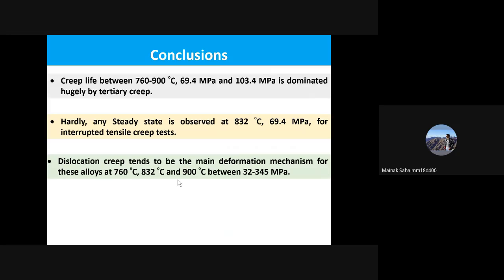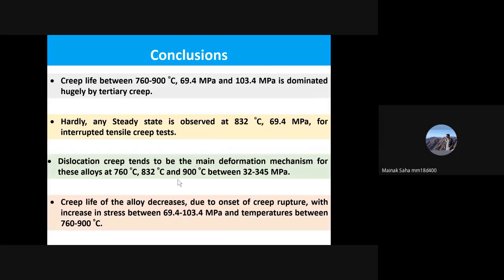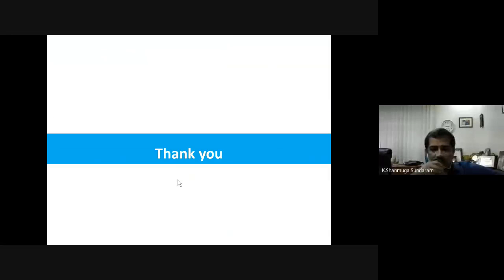Then fourthly, and most importantly, the creep life of the alloy decreases due to the onset of the creep rupture, which I have discussed in the earlier slide, with the increase in the stress between 69.4 to 103.4 MPa and at temperatures between 760 to 900 degrees. So with this, I would like to conclude my presentation for today. Thank you. You can go to the previous slide. Yeah, sure.